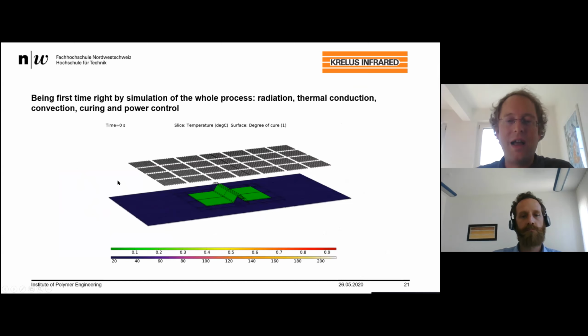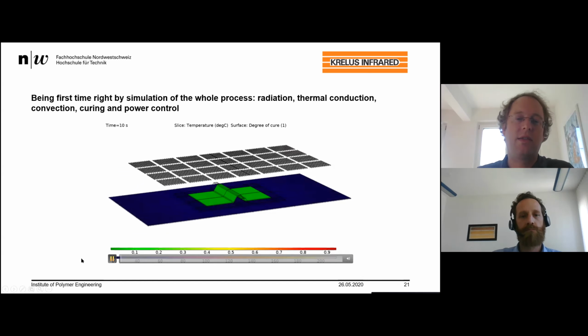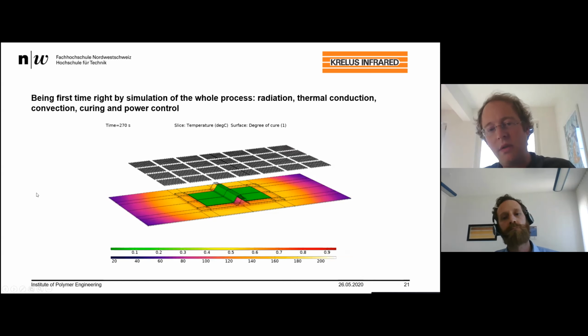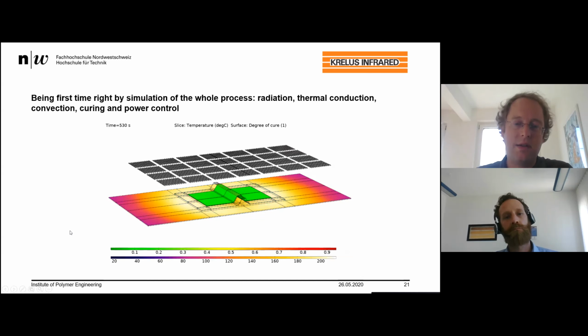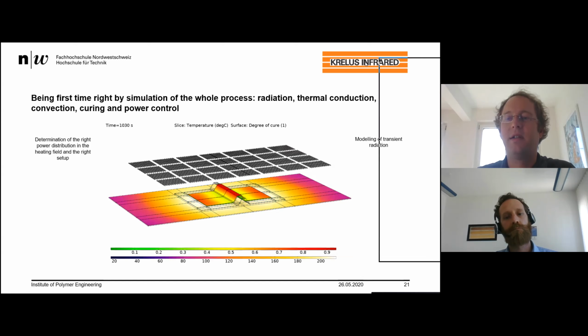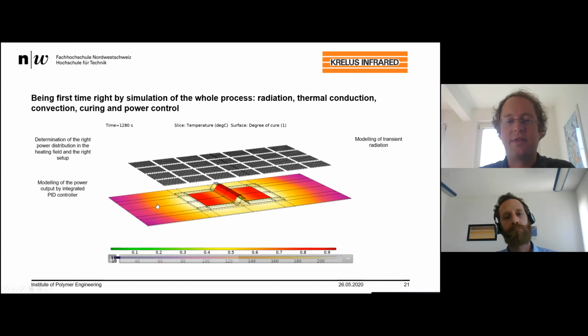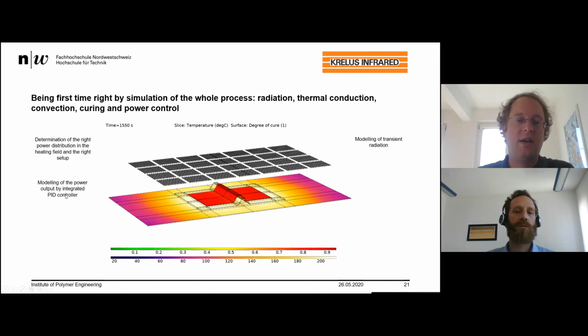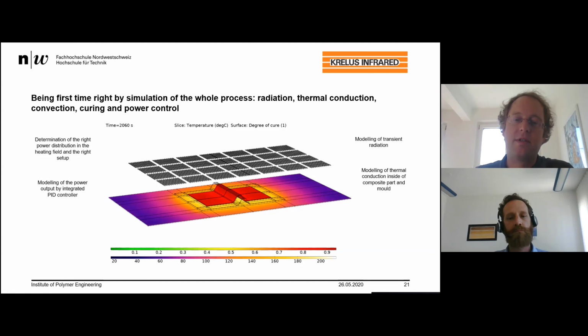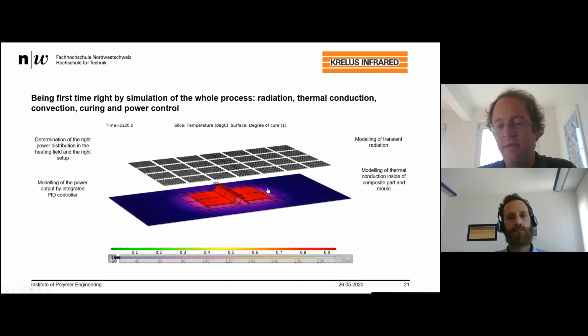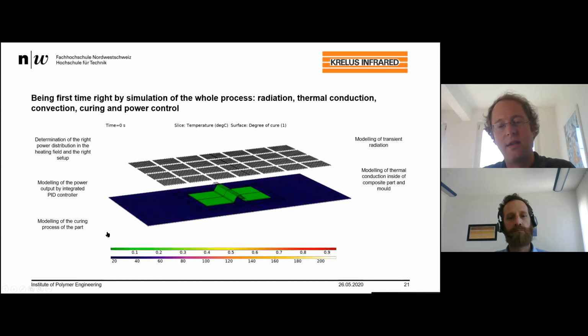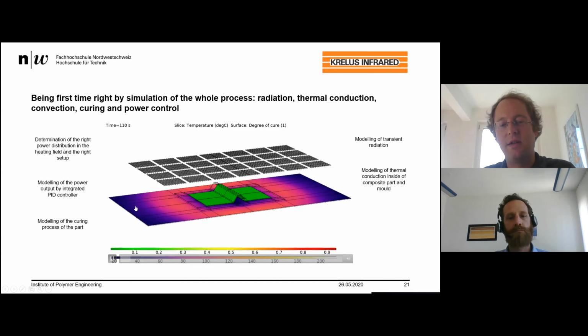And so how have we derived which kind of temperature we have to apply? Therefore, we have built up a simulation which models the radiation. It models as well the control system, because the temperature in the filaments has to be defined by this control system. And we modeled the temperature in the part and the setup itself, also in the vacuum setup. And we added the curing process. So in this animation, you can see the temperature and also the curing of the part itself.